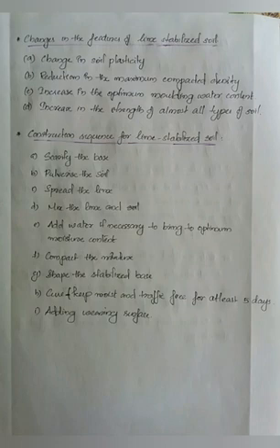The following are the construction sequence of lime stabilized soil. First step is to scarify the base, that means to break up the surface of soil or pavement. Second step is to pulverize the soil. Then lime is spread over the soil. After spreading the lime, we have to mix the lime and soil. Fifth step is the addition of water if necessary. Add water, this is to obtain the optimum moisture content.